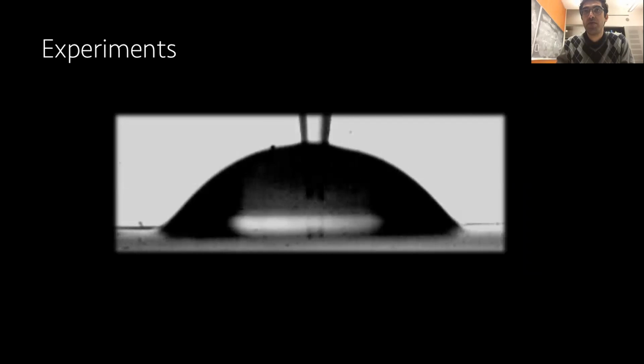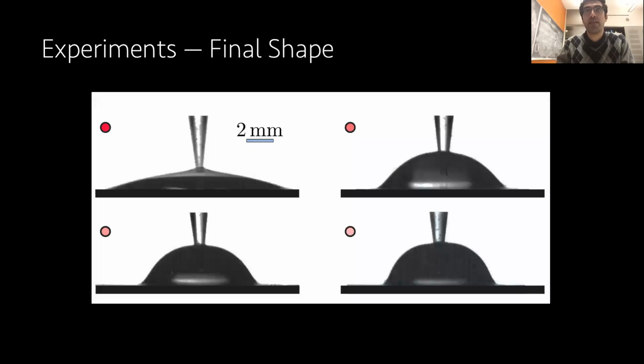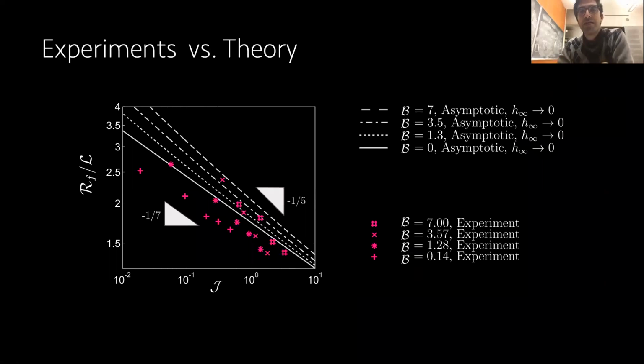This is what a video of an experiment looks like. You inject the fluid, the droplet grows, and you stop the pump, the droplet relaxes and gets to the final shape, which looks like this. From top left to bottom right, I'm increasing the yield stress. Sorry, I forgot to mention the exact values, but you can see as the yield stress increases, the final radius drops. So we measure this final radius, and it's time to compare it with our asymptotic solutions. Here is some comparison. The lines show my asymptotic limits for different Bond numbers, and the symbols show the experiments, also for different Bond numbers.